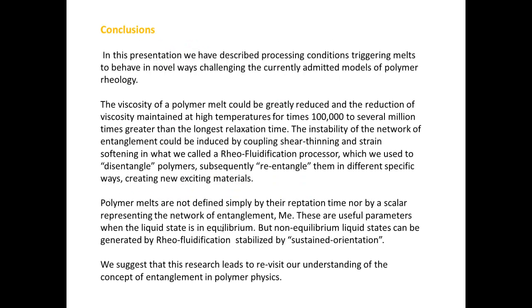Conclusions. In this presentation, we've described processing conditions which trigger melts to behave in novel ways, challenging the currently admitted models of polymer rheology. The viscosity of a polymer melt could be greatly reduced, and the reduction of viscosity maintained at high temperature for times 100,000 to several million times greater than the longest relaxation time. The instability of a network of entanglement could be induced by coupling shear thinning and strain softening in what we described as a rheofluidification processor, which we use to disentangle, quote-unquote, polymers, subsequently re-entangle, quote-unquote, in different specific ways, creating